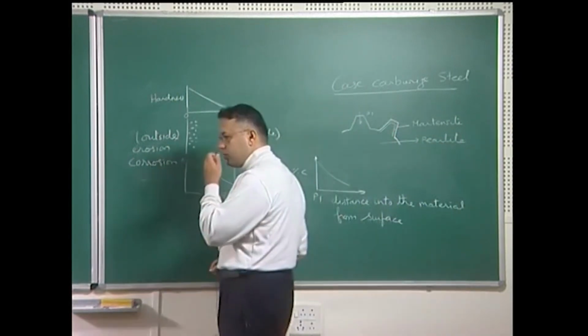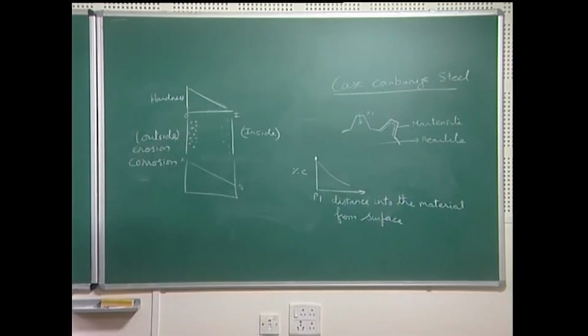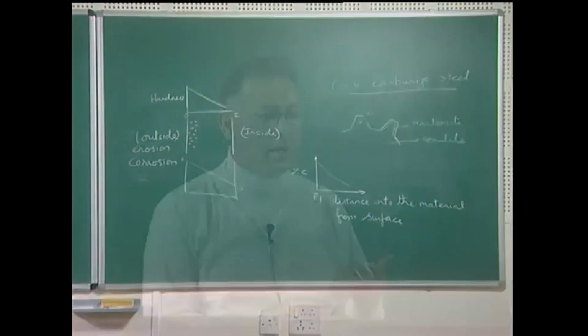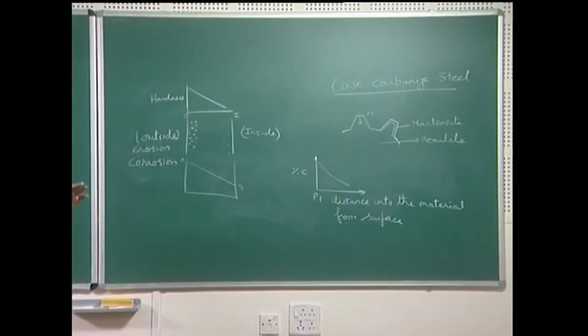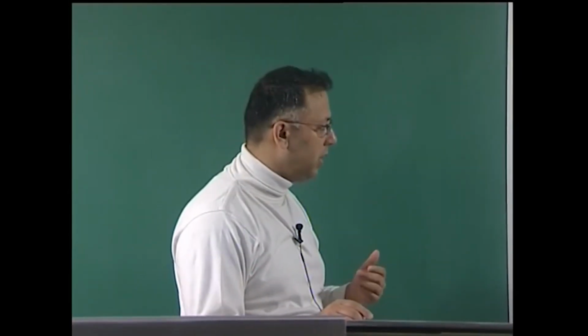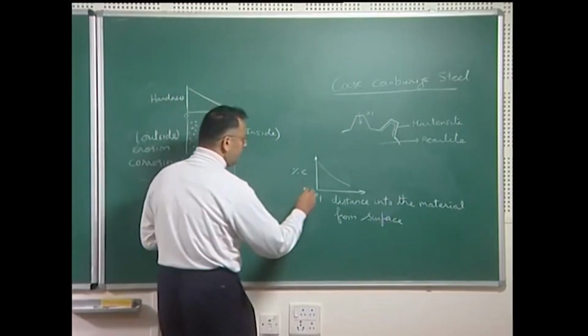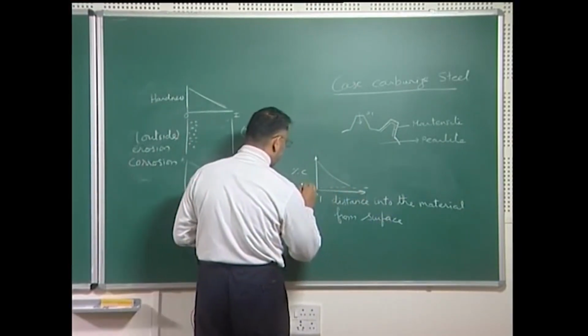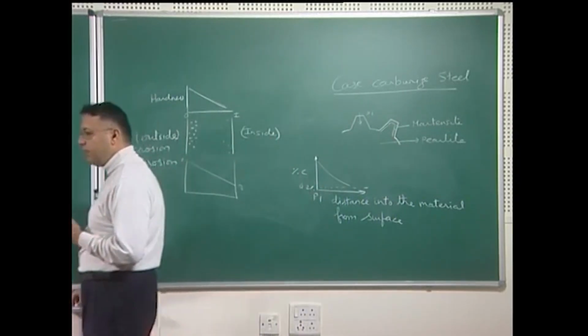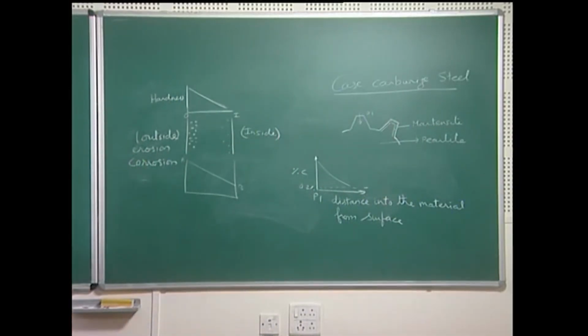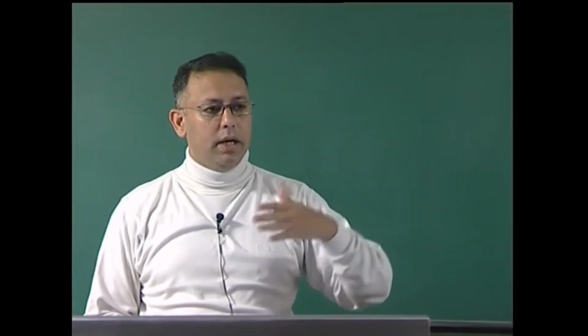The reason for this variation in microstructure is related to the cooling rate. The surface feels a very high cooling rate, or a high quenching rate, which implies that the high carbon in the interstitial solid solution forms a martensite, while the interior is facing a low cooling rate, which gives rise to pearlite. And this pearlite on the interior side also has a lower amount of carbon, similar to the original carbon in the material, which I could call something like 0.2% carbon. And therefore, I will have a material in which the surface is extremely hard and the interior is tough.